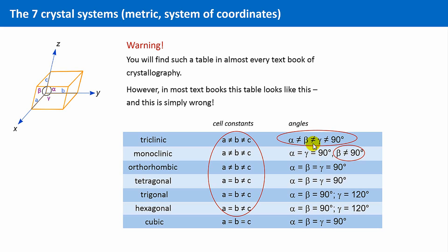These circled entries are wrong. Of course, it is not very likely that the angles are 90 degrees for the triclinic system, but it is not forbidden. The angles can be indeed coincidentally 90 degrees, even for the triclinic crystal system. And this means, that the crystal system is not determined by the cell length and angles, by the metric, it is determined by its symmetry.